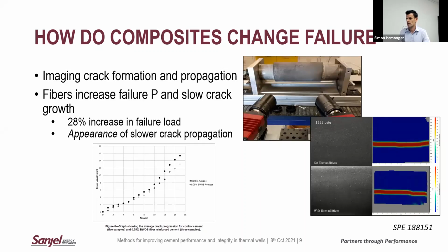The top sample there is a standard thermal cement without any fibers, and the bottom one is with the addition of fibers. And a couple of things that you see here is that we do get an increase in the total failure load, approximately 28% increase in the pressure at which failure occurs, and also the appearance of slower crack propagation. You can see that at the top image, that crack seems to propagate quite quickly across the screen, whereas in the bottom image with the fibers, that seems to be a slower, more ductile process.